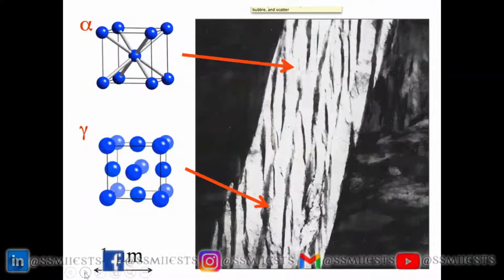Now this is an interesting picture where we have both ferrite and austenite. The ferrite is bainitic ferrite, very, very thin plates of bainitic ferrite. You can see the scale marker there. They're about 1/4 of a micrometer thick. And the austenite is retained simply by the partitioning of carbon. Okay, so it's an extremely cheap form of austenite. Carbon is very cheap. And what we have is a beautiful composite of ferrite with austenite in between.